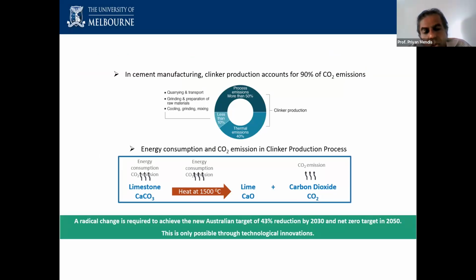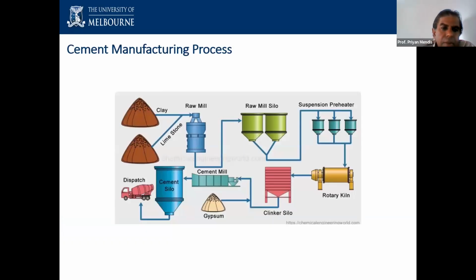But with the limestone, the reason is that in cement production, calcium carbonate is heated to around 1500 degrees in the cement production process. To convert it into lime, CaO, it emits CO2 when CaCO3, calcium carbonate limestone, is heated at very large temperatures. Again, I will not go through the cement manufacturing process. It goes from clay to limestone to the rotary kiln. That's where the damage happens, at 1500 degrees and all that. You can read about the cement manufacturing process on the web.